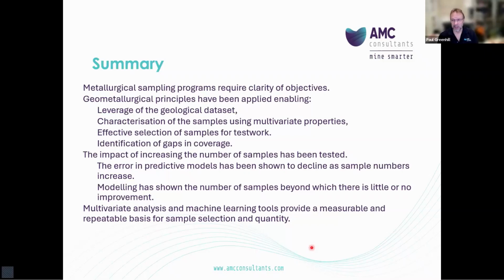So for the target variables tested, drop weight index, both models clearly show a minimum number of samples beyond which the addition of further samples makes little or no improvement to the error in the models. The RMSE, as expected, declines more or less asymptotically to the total error associated with factors including the geological sample heterogeneity, the experimental error, and the error associated with all characteristics that aren't actually captured in the input data.